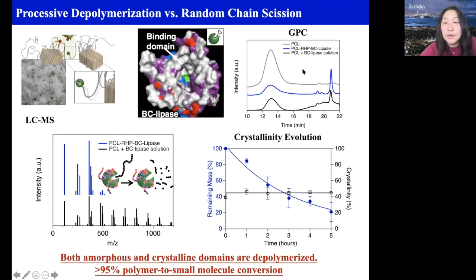So that's the GPC. And then we also want to look into the crystallinity evolution. When you bind to the chain end, you can imagine that it should be fairly straightforward to degrade the amorphous region because the polymer chain has mobility, so it can slide through that pocket.